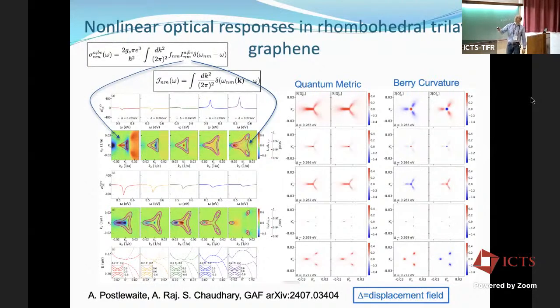And unfortunately, there's not a clear connection that we could discern. There's a lot of convolution of joint densities of states, matrix elements between bands, et cetera. So the picture is rather complicated in the details. The result that we were seeking was that we could identify, hopefully, even momentum-resolved information about the quantum metric by looking at sign changes in the optical conductivity. We weren't able to reach that conclusion in this particular case.